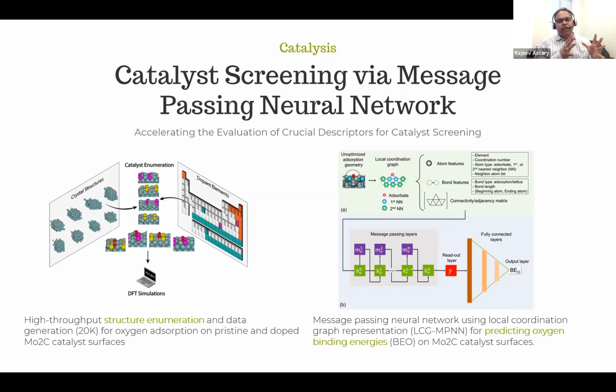So we used that data as the data for the oxygen binding energies. But for the development of a machine learning model, what we used is an unoptimized adsorption geometry, not an optimized structure. So all you need to provide is a graph of the binding structure, and you produce the binding free energy of oxygen, so that we can understand the binding free energy of any given site of any type of this catalyst.